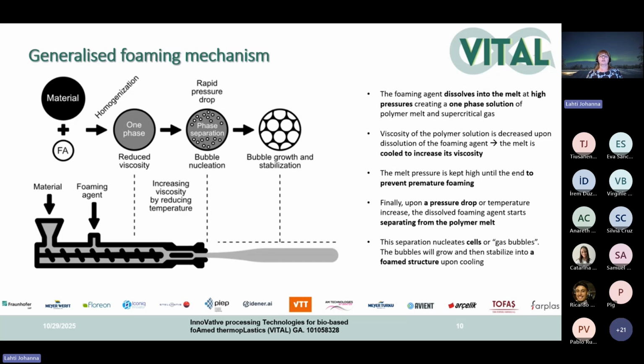So the foaming agent dissolves into the melt during the extrusion, and then it creates this one phase solution of the polymer melt and this gas, for example. And what are important parameters during this process is, for example, temperature, what we are using in extrusion, and what is the pressure used in this process. We are affecting the viscosity during this process. So first, the viscosity is decreased, and then in the end, the melt is cooled to increase the viscosity. And it is important to follow the pressure during the process so that we prevent premature foaming, because we don't want it to happen too early.